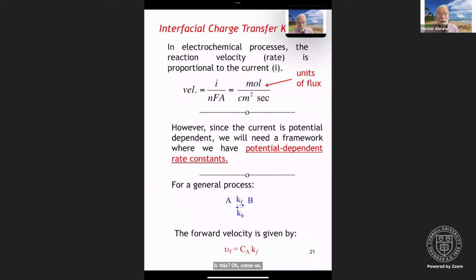Okay, so we begin our discussion of interfacial charge transfer kinetics. As we mentioned, in electrochemical phenomena, the reaction velocity or the rate is proportional to the current, right? If we look at the velocity, we can say current divided by nFA: number of electrons, Faraday constant, and area. Dimensionally, it's moles per centimeter squared per second. That has units of flux. And so basically what we're saying is when we look at a current density, we're talking about the flux of material being exchanged at that interface.